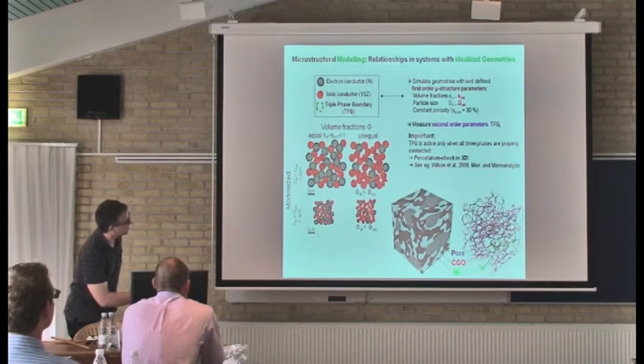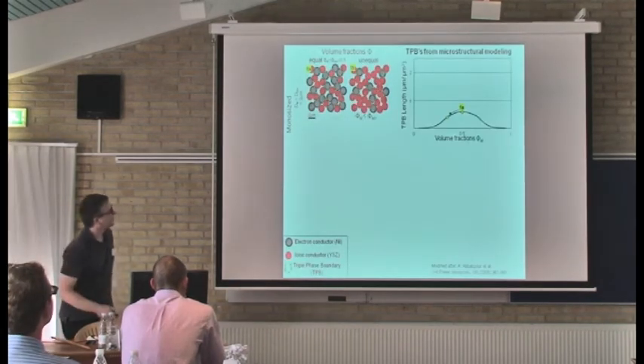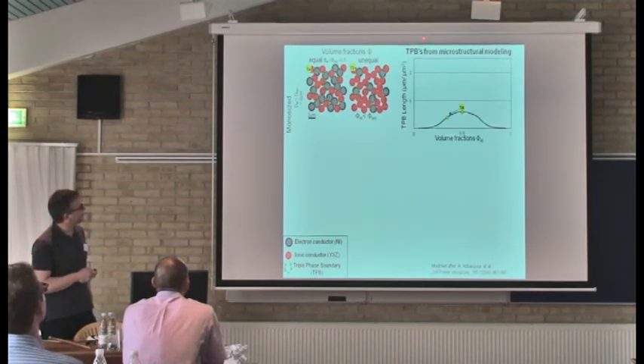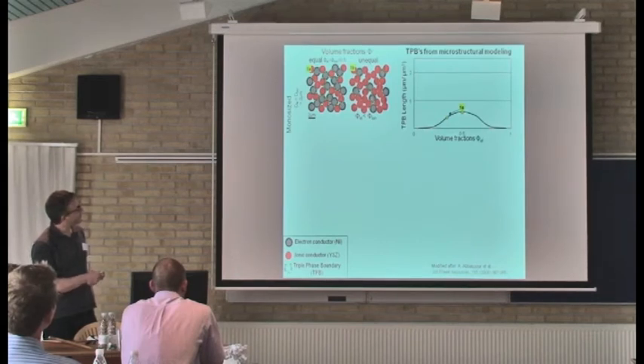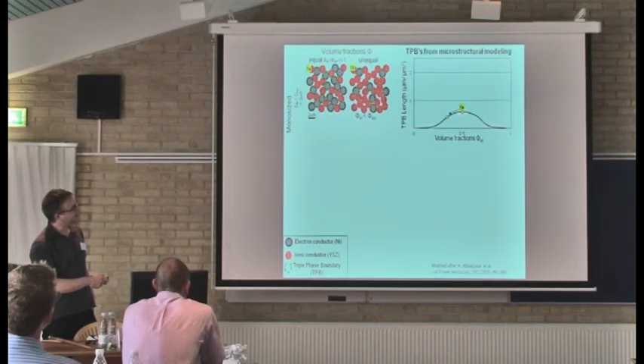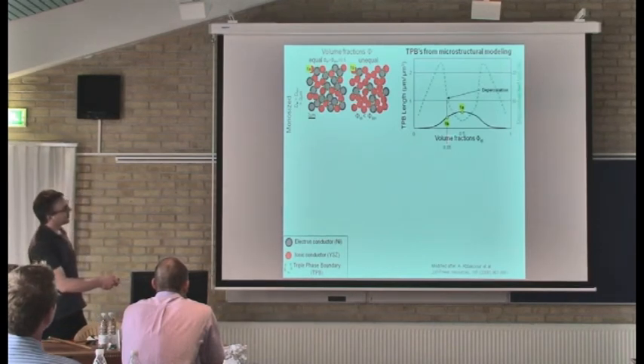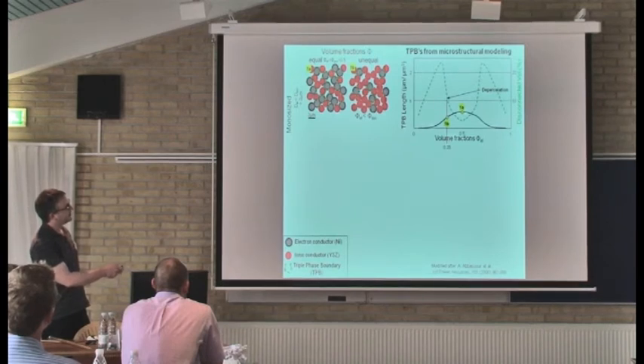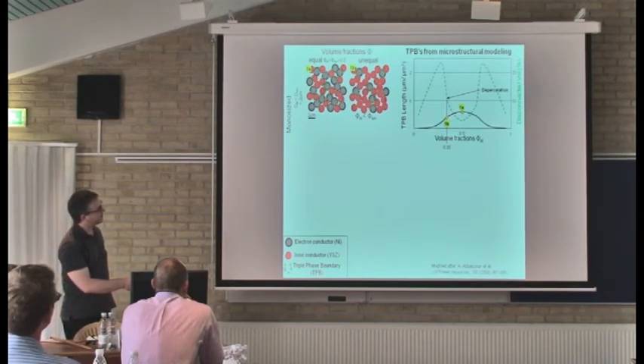This is very nicely treated in a recent publication. These models tell us, qualitatively at least, that when we change the volume fraction of nickel we get distributions of TPBs like this. When the size of the nickel and of the ceramic phase is the same, we have a symmetrical curve with a maximum at the volume fraction of 0.5. Once we go to volume fractions close to the so-called percolation threshold, part of the material gets isolated — shown here as the amount of material which is percolated and not connected anymore — and then in this area the TPBs are not active.